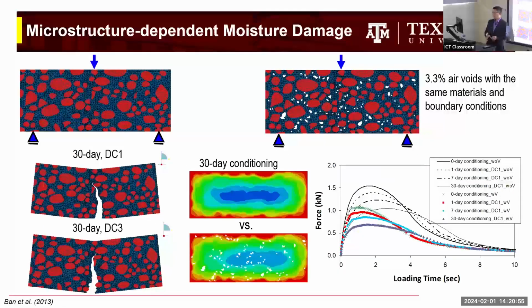And we can do the same job to see the effect of microstructure, like, what if we have air voids, which is true. What if we have aggregate-matrix interaction more sensitive to water or not, like hydrophilic or hydrophobic? Let's say limestone is more of a hydrophobic aggregate, and siliceous gravel is more of a hydrophilic aggregate. When we use different kinds of aggregates, then your fracture pattern will be very different, either cohesive or adhesive, due to water penetration and the diffusion process. So the model can take care of that.